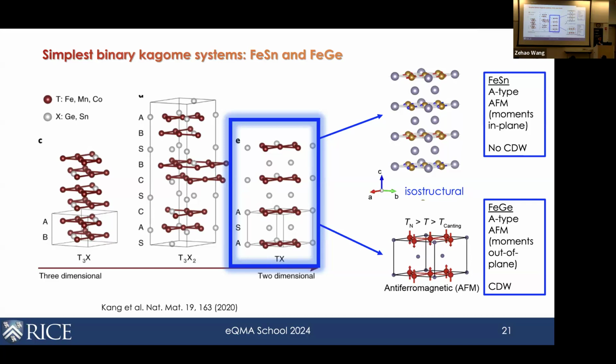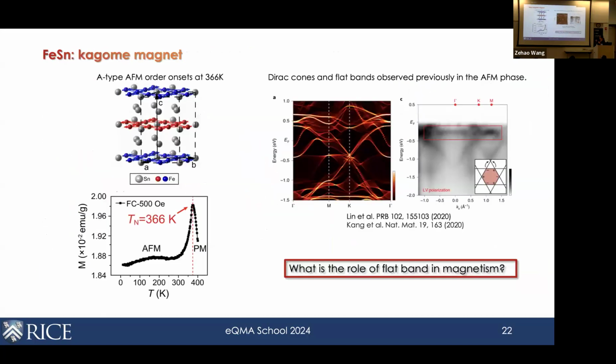Interestingly, so we're going to start with a simpler one, which is iron tin. Because iron tin only has one order, and that is this magnetic order. So iron tin, I reproduce it here, has an ordering temperature about 366 Kelvin. This is what's measured on the bulk crystals. And this has been studied by various groups in the past in single crystal form.